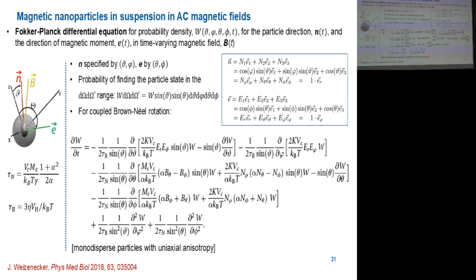it is based on the dynamic magnetization in an alternating magnetic field, and the simple, straightforward view is provided by the Debye theory, but the Debye theory cannot describe rigorously the dynamic magnetization, and you have to apply this approach, for which you need to run some simulations, and there are also many parameters involved. You need to determine magnetic anisotropy. Of course, we have there the relaxation times, both the Néel relaxation and Brownian relaxation. We have there spontaneous magnetization. But using suitable numerical methods, it can be solved.